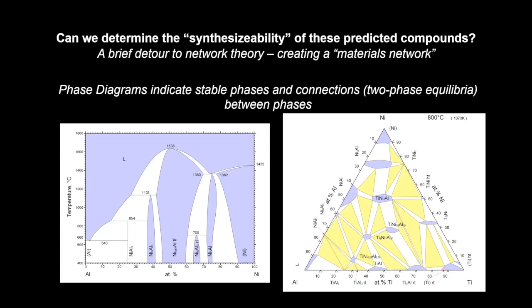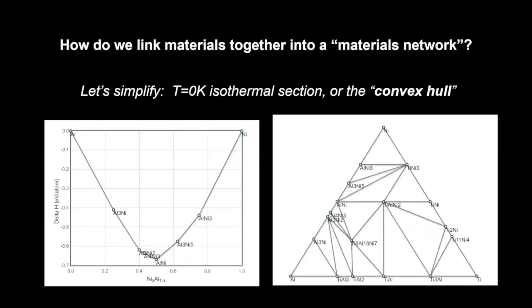Okay, so these phase diagrams tell us something about connections between materials. I'm going to simplify the problem because we're doing DFT. So I'm going to basically say, let's take the T equals zero isothermal version of these phase diagrams, or the convex hull. Again, the convex hull of a binary system could be illustrated by a composition energy plot here. And the convex hull of a ternary system is indicated where I've just projected out the energy axis, but shown this on a Gibbs triangle. Again, the convex hull indicates the stable phases. It indicates tie lines, which indicate two-phase stability between phases. And so this starts to look like a network.